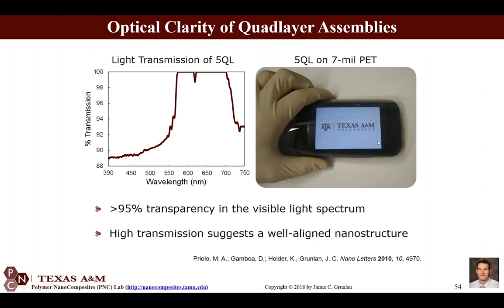So here's a 5 quad layer film. This is less than 100 nanometers thick, and you can see it's completely transparent. That's on top of that PET film there.